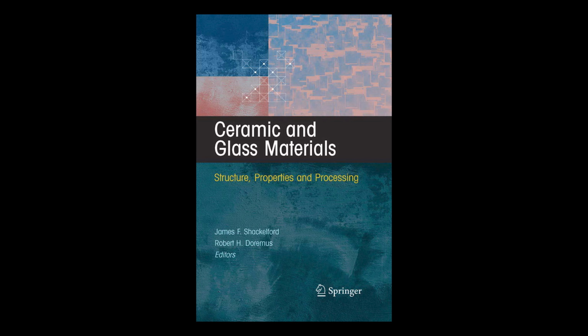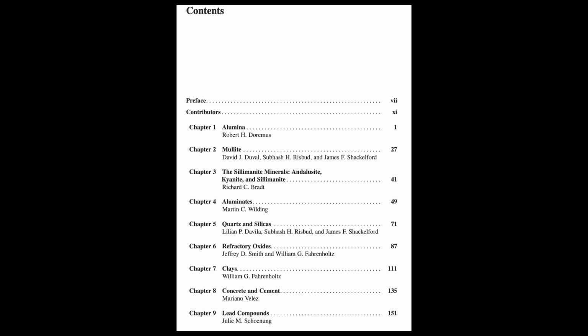And bringing it back to the visuals, those amazing colors in sapphire gems, that's not pure alumina, is it? Exactly. That magnificent deep blue of sapphire comes from tiny traces of iron and titanium impurities mixed into the alumina crystal. Impurities causing color. How does that work? It's a process called charge transfer. Basically, when light hits the crystal, an electron can jump from an iron ion to a nearby titanium ion, or vice versa. Okay. This electron jump absorbs light energy, specifically in the yellow-orange part of the spectrum. And when you remove yellow-orange light from white light, what's left looks blue. Ah, subtractive color. Precisely. And different impurities or combinations can absorb different wavelengths, leading to the whole rainbow of colors you see in sapphires and rubies, both natural and lab-grown.